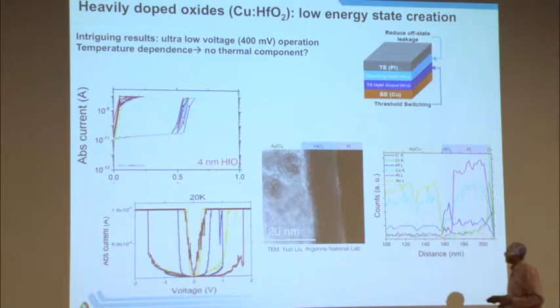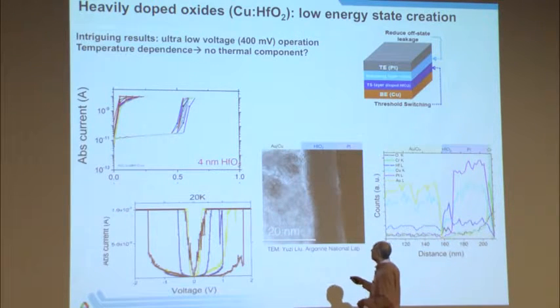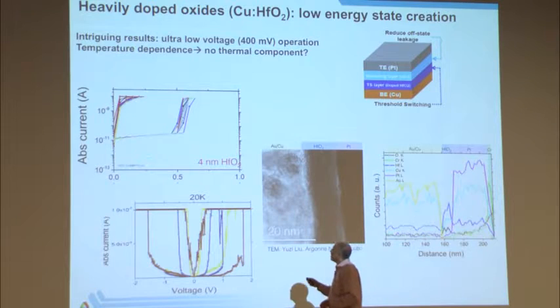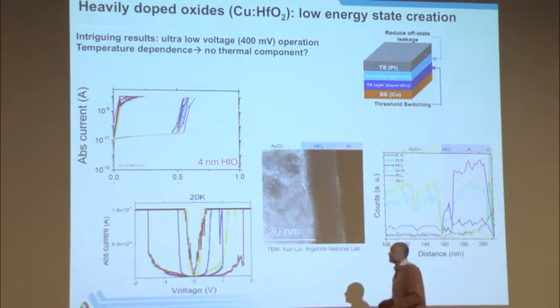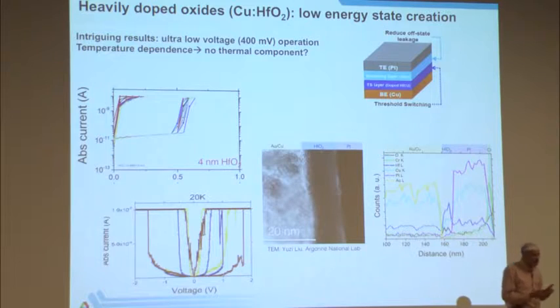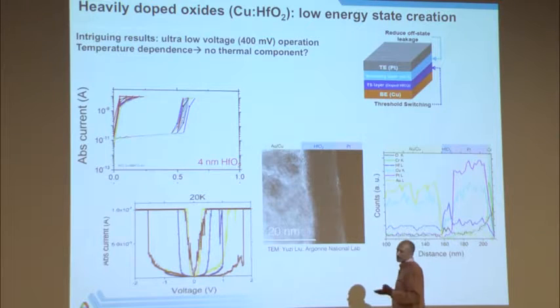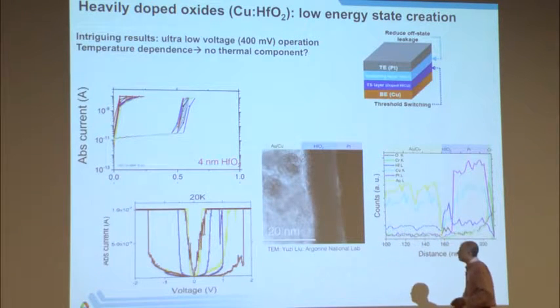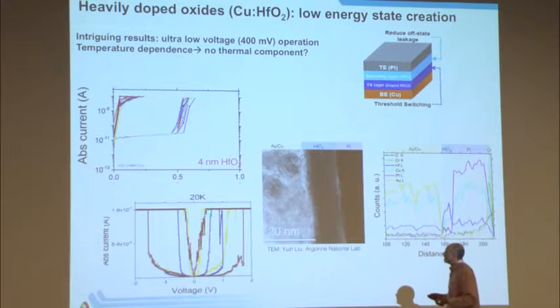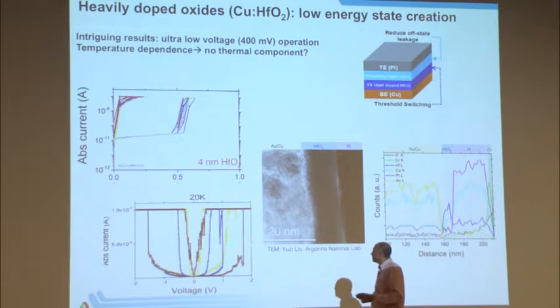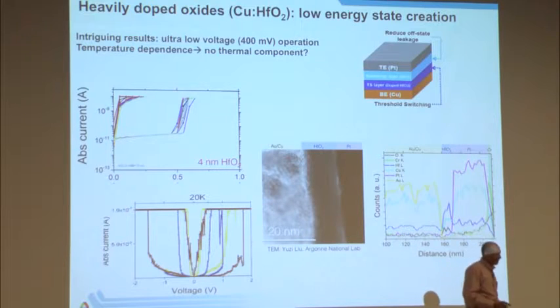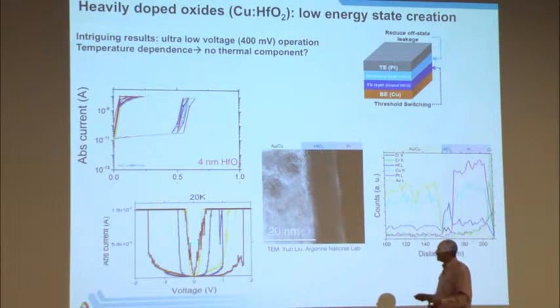A few more interesting things. When we make the hafnium oxide thinner, 4 nanometers, we see much lower voltage operation at about 0.4 volts, which is very exciting to us because usually most of these devices will work at much higher voltage, about a volt or above. The second interesting thing we see is that when we run it at 20 degrees Kelvin, we still see switching behavior. Which is surprising because at 20 Kelvin, if this is a thermally activated diffusion process, then you would not expect this type of thing to happen.